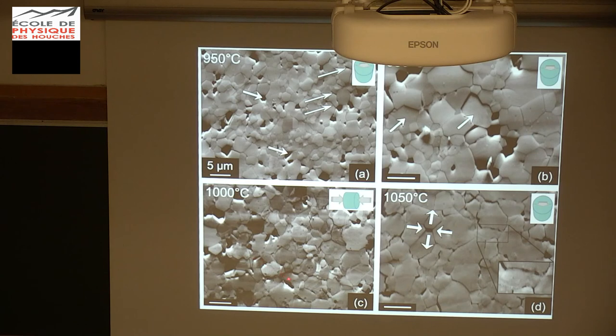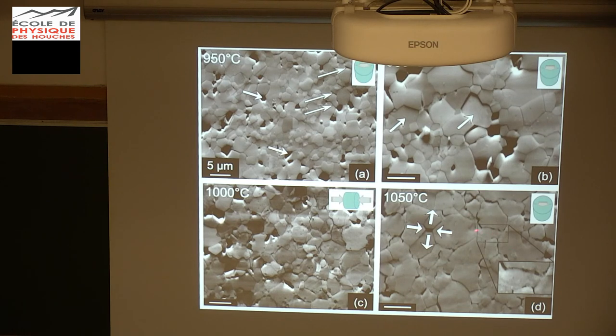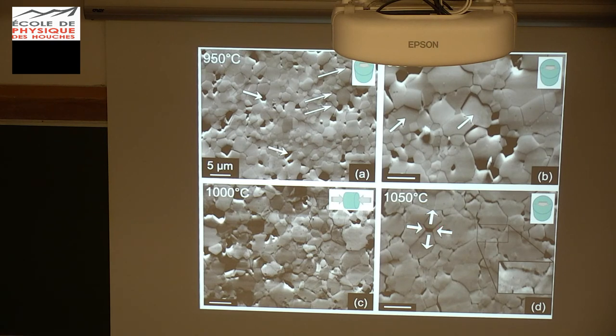We still have those holes — gaps, voids, I don't really know how to call them. And in one sample at 1050 degrees Celsius, we get something that normally we only see in textbooks: nice evidence of grain boundary sliding. We have grain boundaries showing some segregation, and it seems to be everywhere — some very geometrical opening of the grain boundaries. This is the first time we see that in olivine.